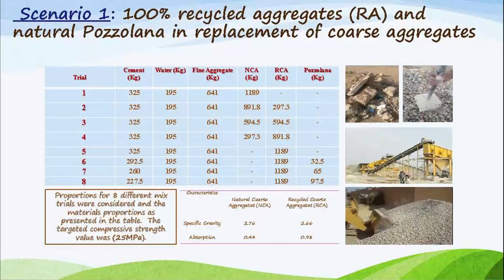If we compare the 8 mixes at 7 and 28 days for compressive strength, the results show that 100% recycled aggregate with 10% pozzolana is the optimum result. If we use recycled aggregate in the concrete mix and add 10% pozzolana as cement replacement, we have the optimum results. And for the slump or workability test of the concrete, we also find the optimum result at 100% recycled aggregate and 10% pozzolana.